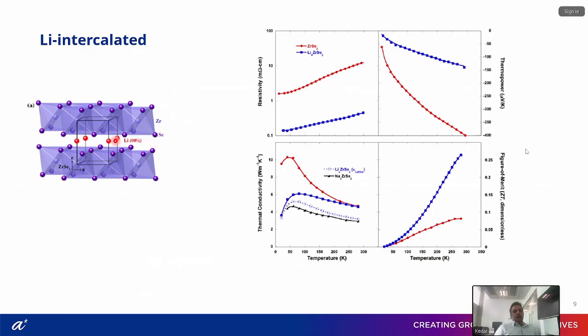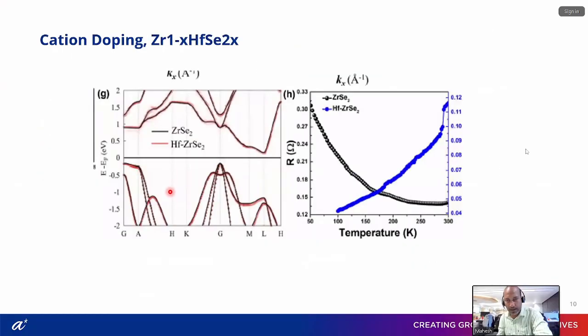But okay, just be careful also with these materials because the texturing will be important. Yeah, texture. With SPS, what Alex did, you can do it in such a way that you enhance the texturing and that gives you anisotropic properties. Yeah, it helps with all this, but it becomes tricky, so I'll be honest, I'm not a big fan of them. Doping control is okay, but the intercalation and such are also very isotropy dependent. So choose it carefully. There's a lot you can do. But yeah, intercalation is the last option to tune further. Yeah, even this compound is very interesting.